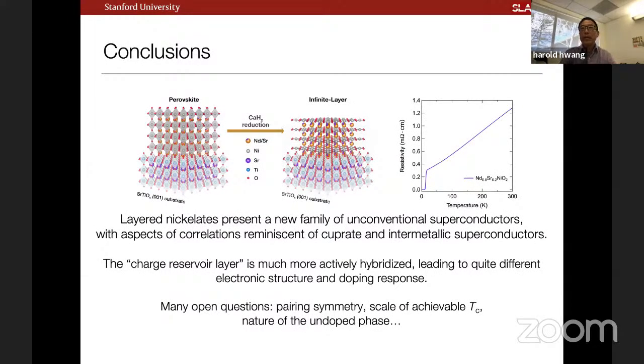I guess I have a bit of time, so maybe I can squeeze one more thing in. But just to summarize, the layered nickelates are an exciting new family of unconventional superconductors. There are aspects of correlation effects that are reminiscent of the cuprate problem, as well as intermetallic superconductors. A key qualitative difference here is that the charge reservoir layer of the cuprates is much more active in this case. It's not simply a source or sink of charge, but it appears to be actively hybridized in the relevant electronic structure. And we think this is leading to some of the important qualitative differences in the doping response.